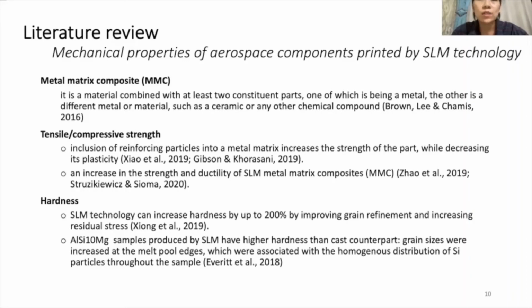So it's well known that the main goal of composites production is to enhance mechanical properties, and one of the main properties of aerospace components is the hardness of material. In this state, selective laser melting technology can increase hardness by up to 200% by improving grain refinement and increasing residual stress. Metal matrix composites deposited by selective laser melting technology present extraordinary features such as high strength at elevated temperature, improved hardness, better fatigue, and creep characteristics in comparison with traditionally fabricated counterparts. It makes them potential candidates for advanced technological applications in the aerospace industry.